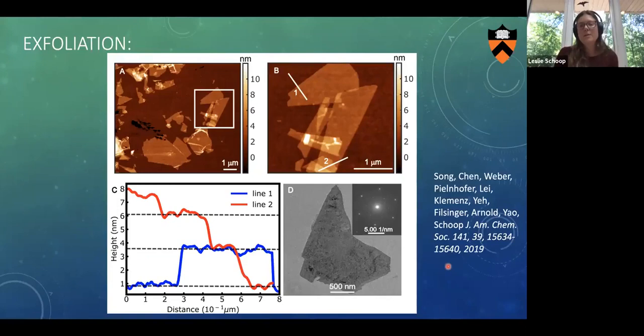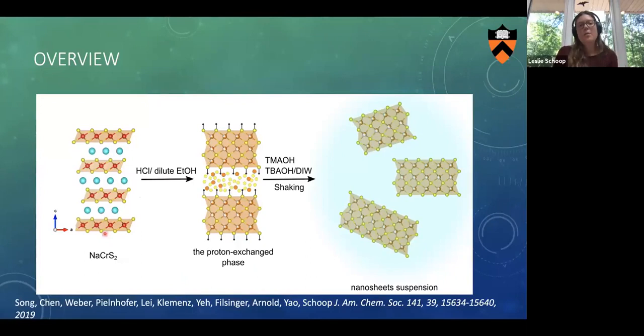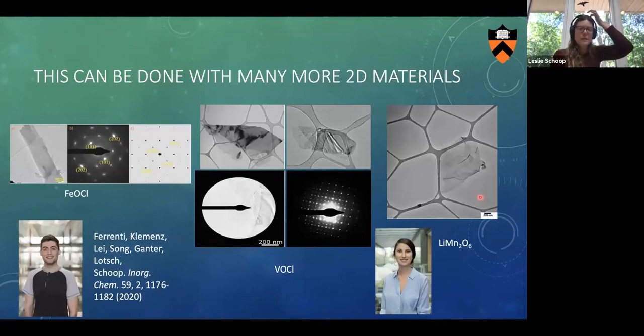So what we ended up doing was not what we originally hoped. What we ended up doing was we made a material like that, an amorphous-crystalline heterostructure, and then exfoliated it into a nanosheet suspension that looked like this. Just want to point out, this is not the only type of chemical exfoliation we do, and it's not always that complicated. We also made magnetic 2D layers of other materials like iron oxychloride, and we have some preliminary data on vanadium oxychloride and some honeycomb manganese oxides that might be exfoliatable.